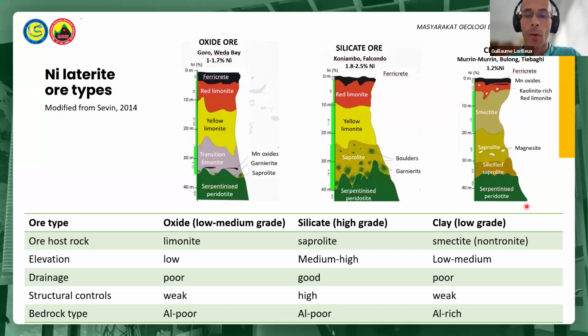The last one, the clay ore, is characterized by nickel-rich smectites, like nontronite, located in the upper part of the saprolite, with an average grade generally between 1 and 1.5% nickel, depending on the cutoff grade again. This type is generally located in low to medium elevation areas with poor drainage, weak structural controls, and high aluminum content of the ultramafic bedrock.